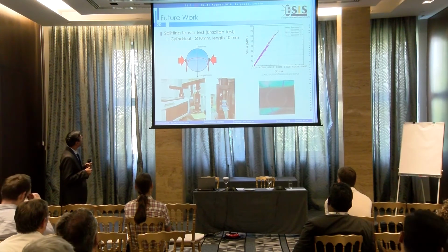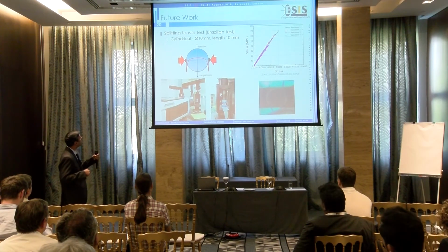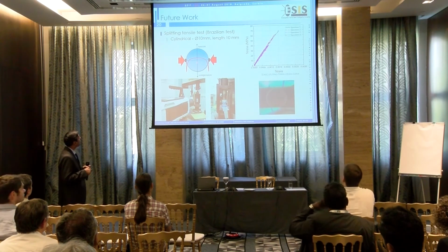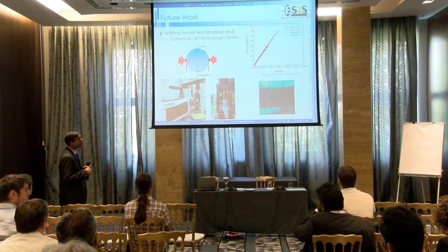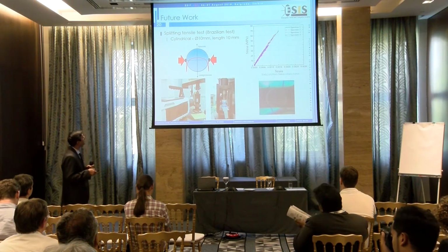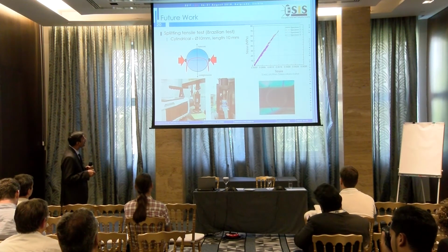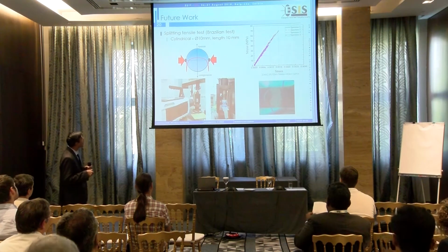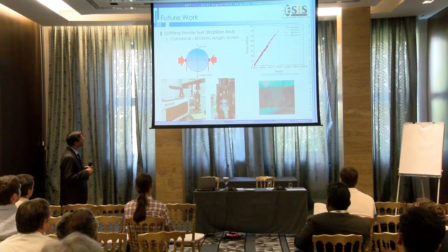So when the damage starts from the center, it splits into two parts. It's very important that damage should start from the center to get the appropriate results. If it breaks from the loading ends, the test is not accurate. I have presented here one of the test videos captured during the test to see the tensile behavior. It splits clearly into two parts.